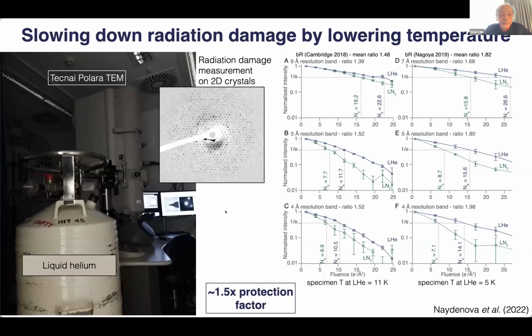I'll just quickly mention what we're working on next. So we've been studying the potential of using liquid helium to reduce the radiation damage to specimens more than we get at liquid nitrogen temperatures. We recently published a paper about this, again in Ultramicroscopy. It's in the current issue, actually, along with 2 other papers on imaging thick specimens. And the potential benefit here is not enormous, but it's significant.